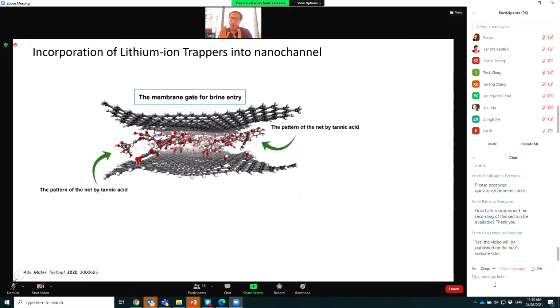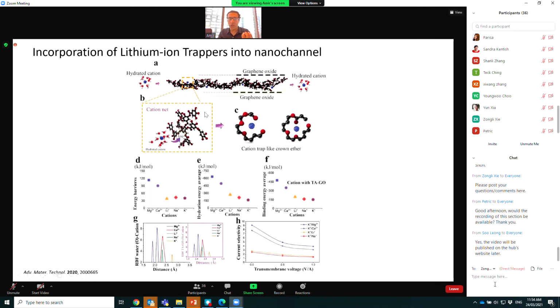In another project, we tried to manipulate the atom-scale space within the nanochannel and also the chemistry of the nanochannel, by incorporating tannic acid in between the graphene oxide nanochannels. The tannic acid has elements and a structure within its molecular structure which behave similar to lithium crown ethers. So these natural cation trappers provide an opportunity for trapping lithium and allowing other ions to go through.